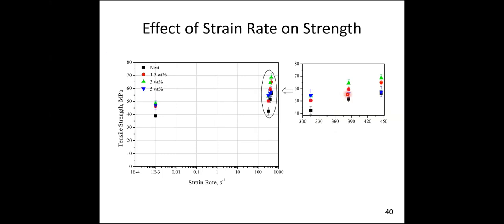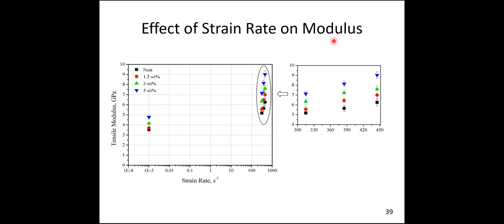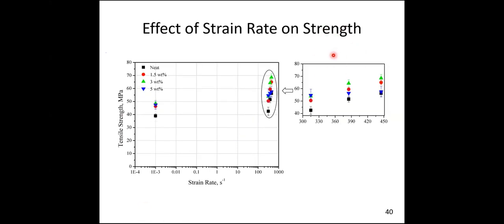Similarly, this slide shows the effect of strain rate on strength. The previous slide showed the modulus, and the next slide shows the strength. Again, for strength we could not get good improvement in the 5% because, as I mentioned earlier, the 3 and 5% lead to agglomeration. Because of agglomeration, the sample led to premature failure, and some voids were also formed because of the higher content of clay.